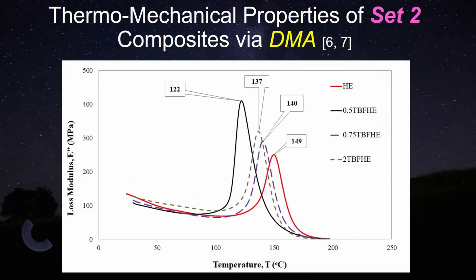And this is a similar test we have done for the set 2 sample, and that's the interesting result we found. The interesting result is that HE over here, the heat resistant epoxy, got the highest Tg value, which is 149. However, even after incorporating treated fiber, this value reduced, and that is the indication that biofiber has a limitation. Biofiber has a limitation. It should not be used for high heat resistant applications. They have a limitation, and that's the constraint we found.